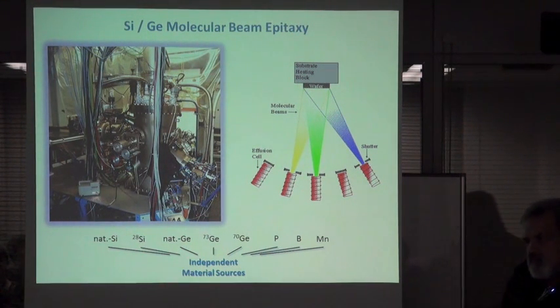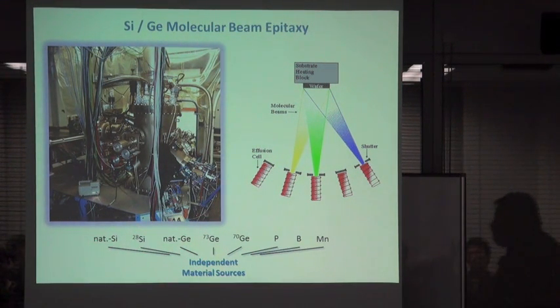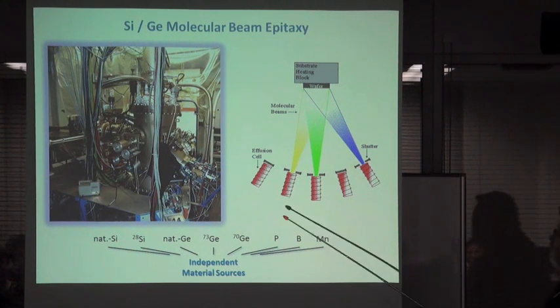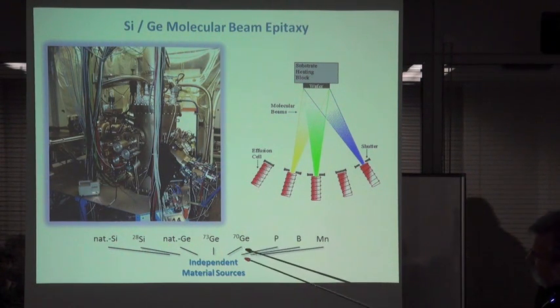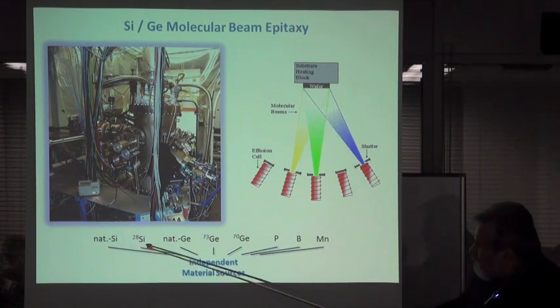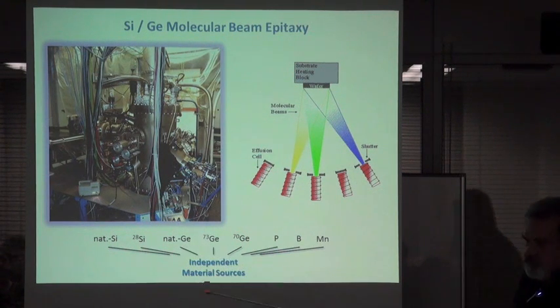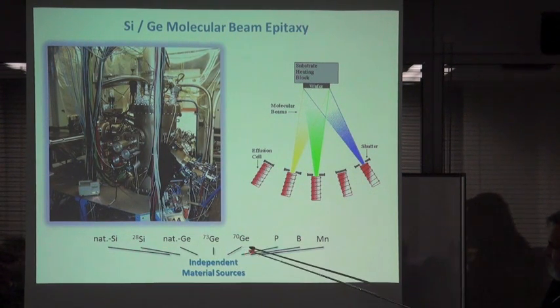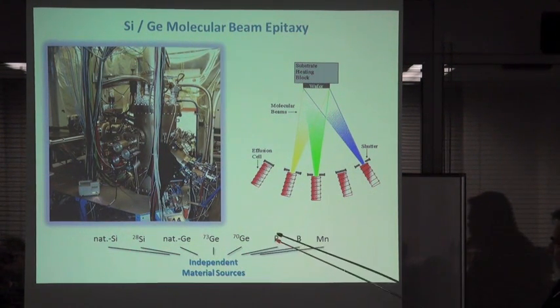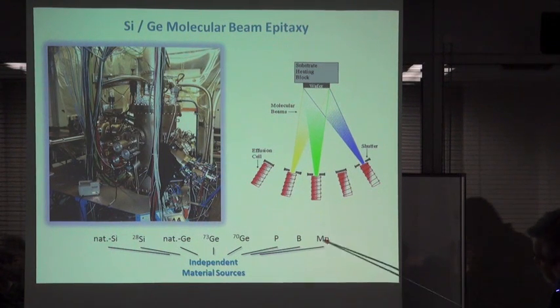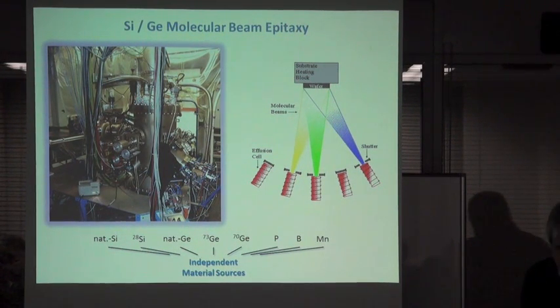Now, one of our MBE machines is silicon germanium based, not just III-V based. And in this MBE machine, we have natural silicon as a source, silicon-28, natural germanium, germanium-73, germanium-70, and phosphorus and boron, and also manganese for magnetic, which I don't like too much in this machine because it deteriorates the mobility. But we didn't use it for quite some time now, and it's quite good what we get.